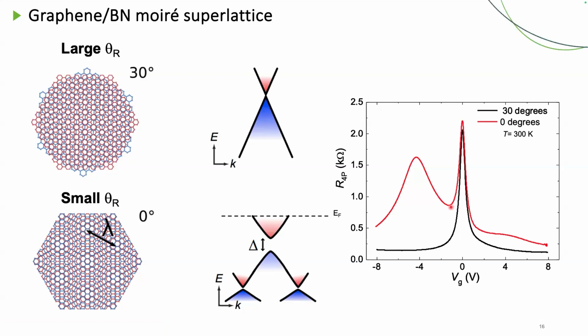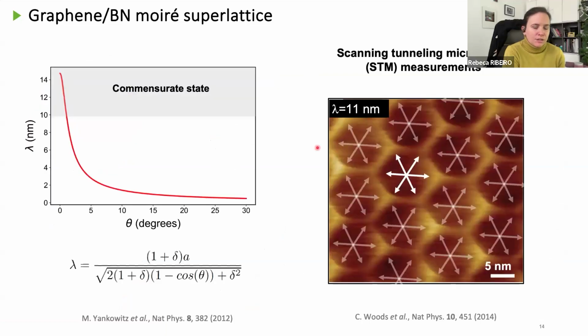The STM images, are they measured in ambient or in high vacuum conditions? Vacuum condition. In fact, it's low temperature STM. It's 4 Kelvin STM. But you can see the commensurate state even at room temperature. You can even see it with AFM. In fact, I'm going to show that in a second.